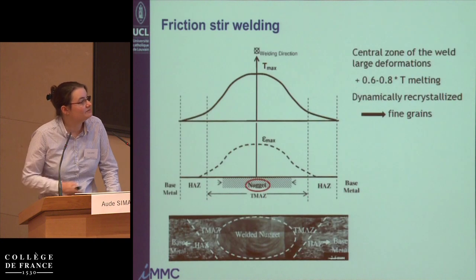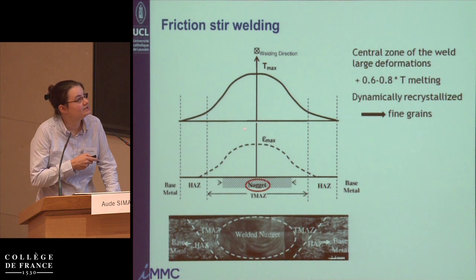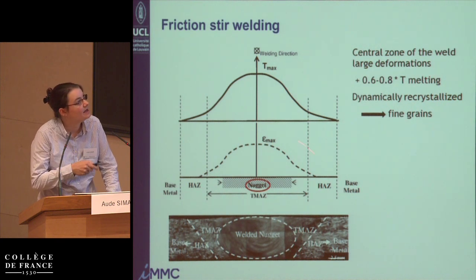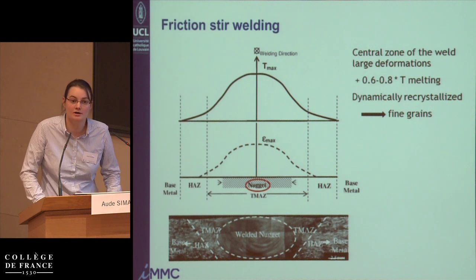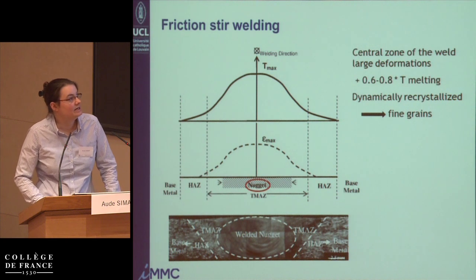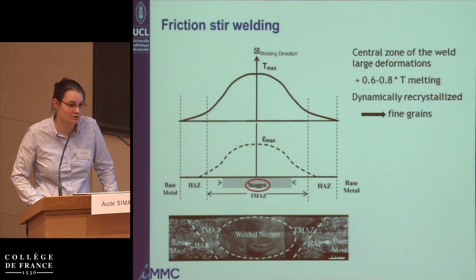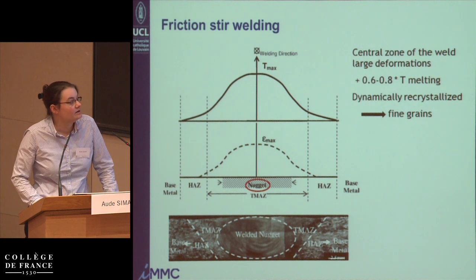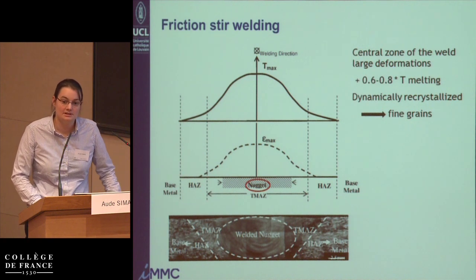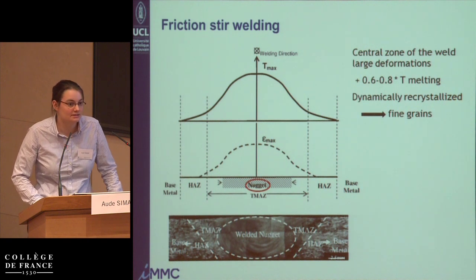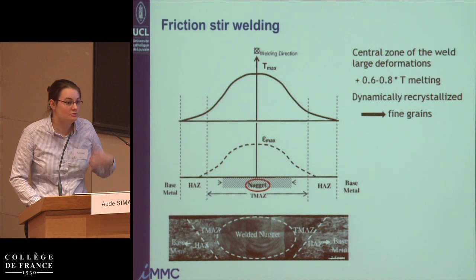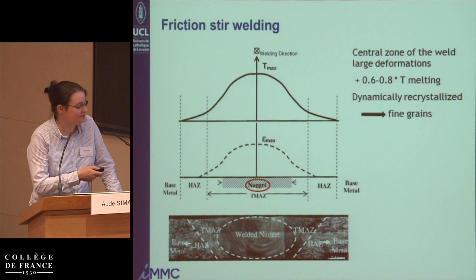So what you have in this nugget zone is very large deformations and large temperature that can go up to 80% of the melting temperature or even higher. That brings the material in a dynamically recrystallized condition, and you will have fine grains in this material.